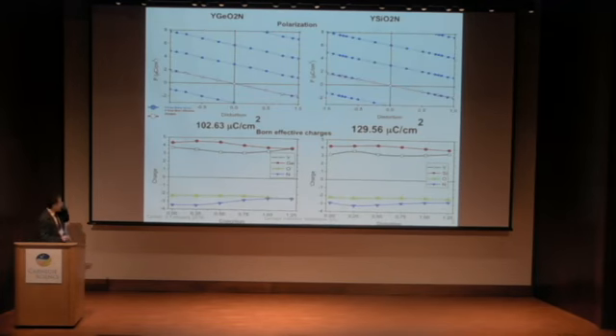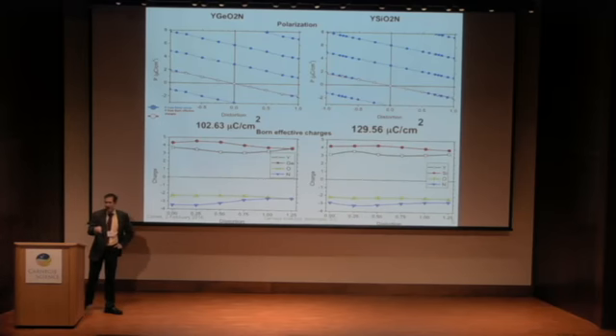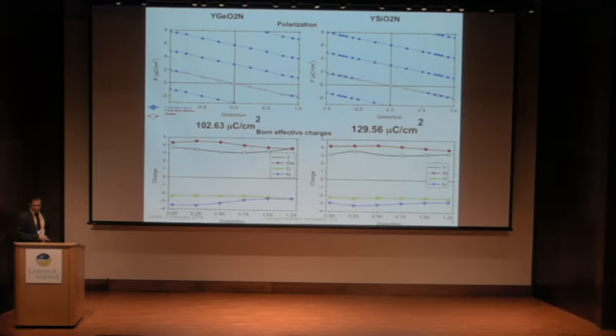So anyway, these two materials, we basically went through and applied all the new technology of the day to calculating its properties. And we calculated, for example, the polarization. So we heard a talk yesterday about a more straightforward way of doing that, which is good. But you see here we used the old-fashioned way of actually tracing out these different polarization branches so that we could see exactly what the polarization was. The polarizations came out so large that you really had to take some care to do this properly, because we actually got the largest polarization, I think, of anything known, at least at the time, and maybe still, for this yttrium silicon oxynitride. So these were very large polarizations and very significant effective charges.